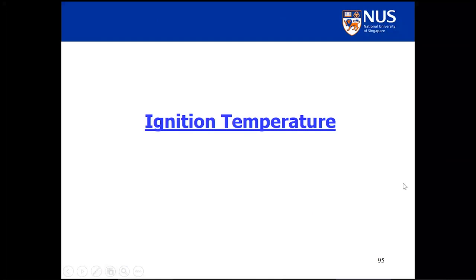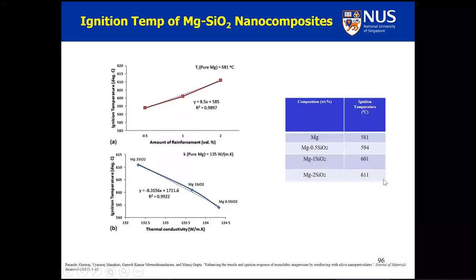Very interestingly, the addition of nano reinforcement also increased the ignition temperature of magnesium, which is at 580 degrees centigrade. And just by putting 2% of SiO2, it increased by 30 degrees centigrade. The reason, the physics, we do not know, but we know that thermal conductivity goes down. And when the thermal conductivity goes down, the ignition resistance is increased.